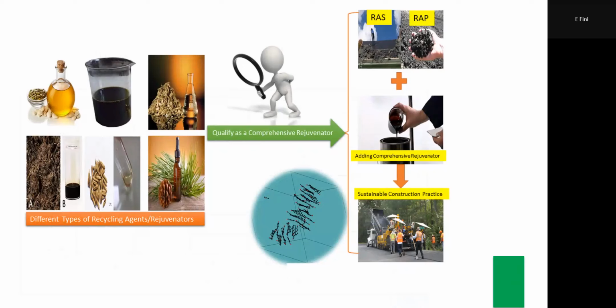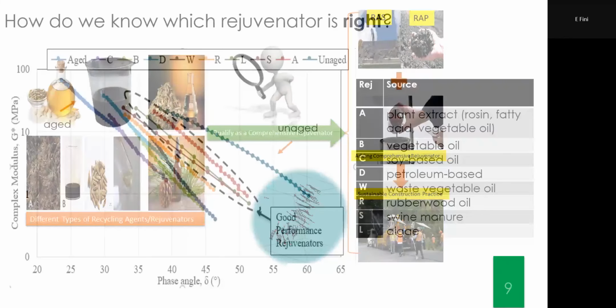One thing I want to caution you about as you research this topic: make sure that you're not losing other properties that are not under as much attention, for instance durability, moisture damage, and aging trajectory. If you pick a rejuvenator that does improve your crack resistance and your healing capacity, does it compromise your moisture damage? Suddenly you get an asphalt pavement that used to have no moisture damage, and now because you added rejuvenator, it becomes susceptible to moisture damage. That's something you have to keep in mind as you add new materials.